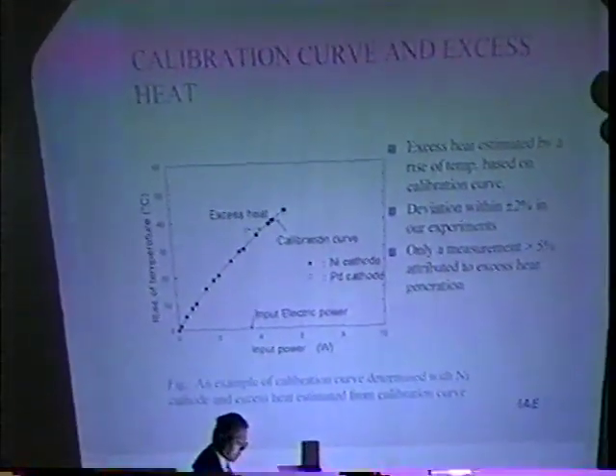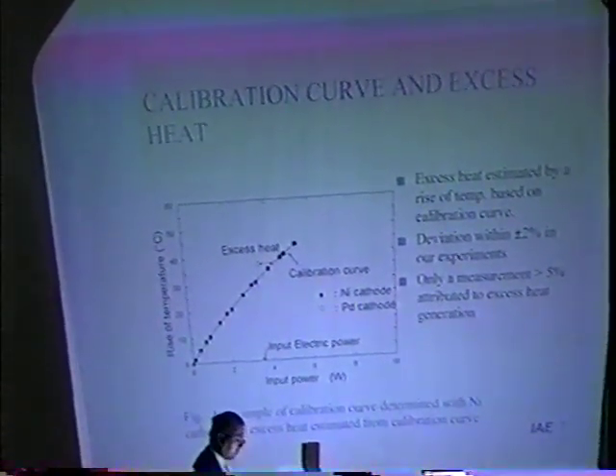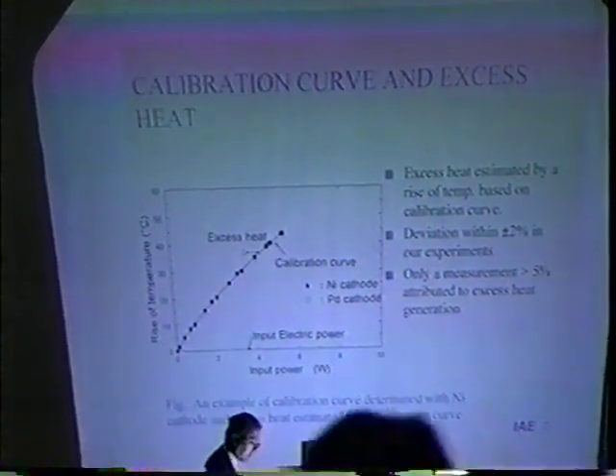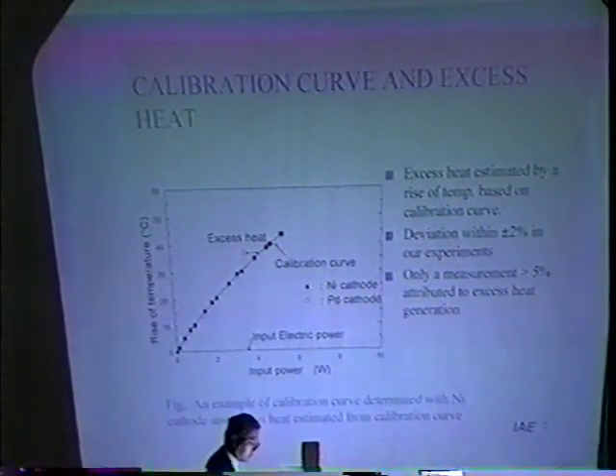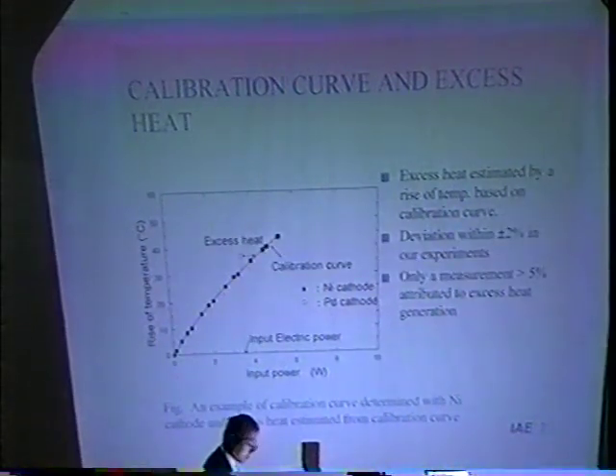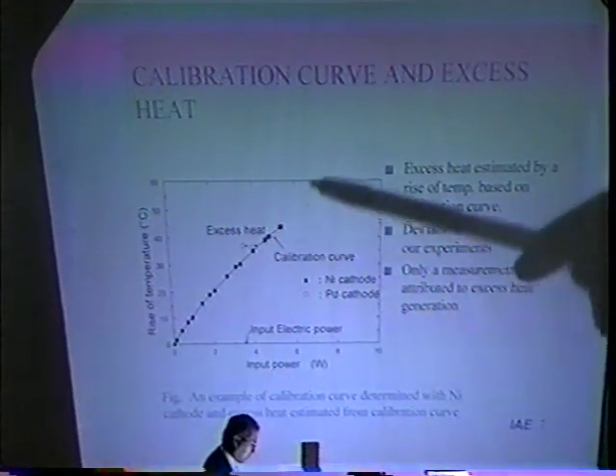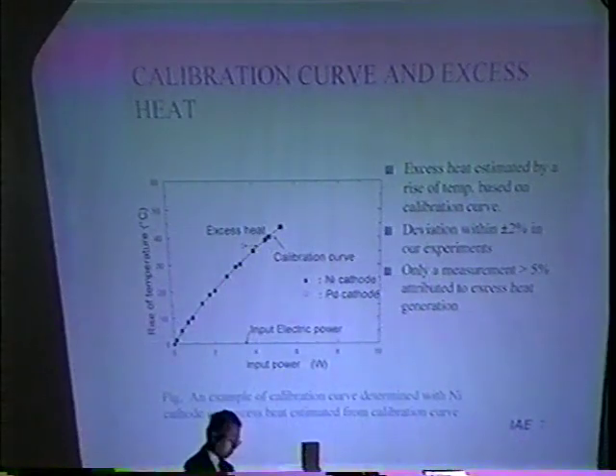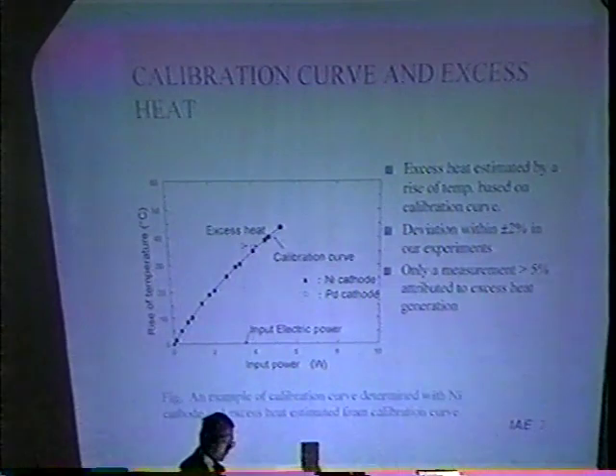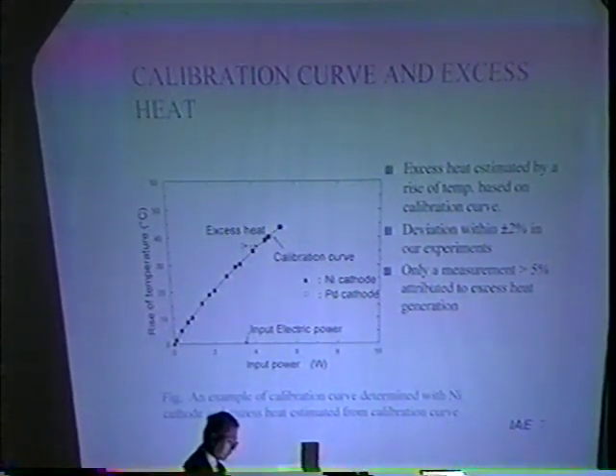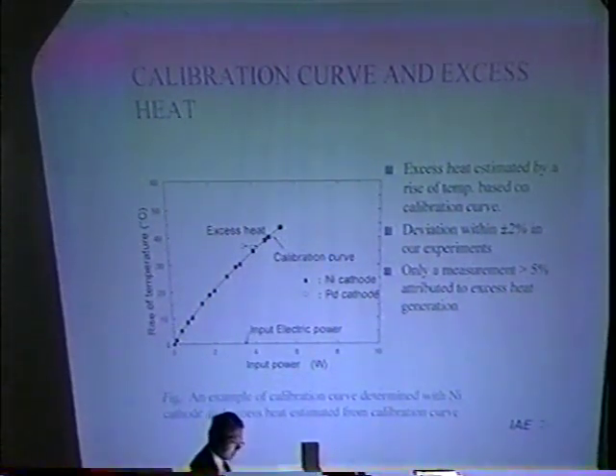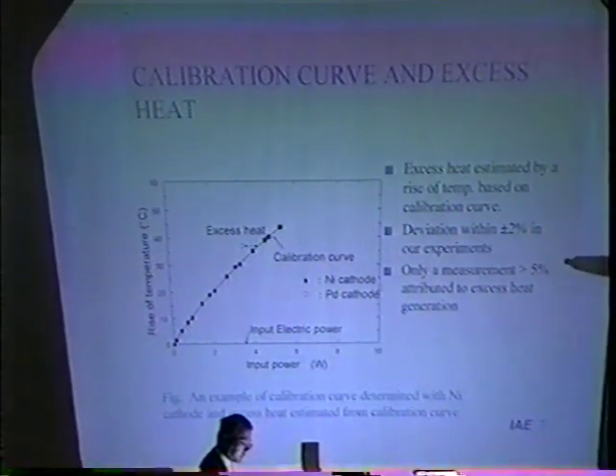This figure shows an example of a calibration curve and excess heat. The calibration curve was determined with a nickel cathode, and excess heat was estimated from the rise of temperature relative to the calibration curve. The calibration curve was previously determined using the dummy nickel cathode. The accuracy of excess heat estimation depends mainly on the accuracy of assembling the cell. We evaluated the deviation of the calibration curve and concluded that it was within plus minus 2% in our experiment. This value is plus minus 3 sigma of deviation. Therefore, only a measurement larger than 5% is assumed to be attributed to excess heat generation.